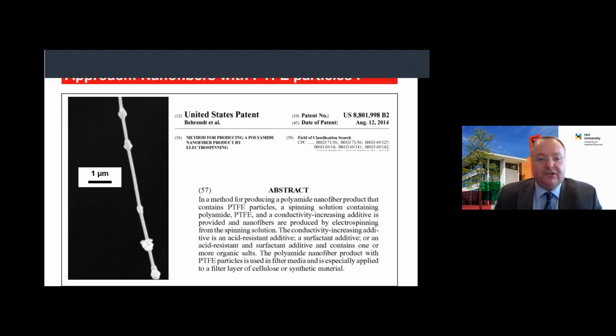Okay, here you see such a fiber. It's also an SEM picture. Here are PTFE particles. We have evidenced the presence of these PTFE particles with EDX. We could see that there is a lot of fluorine here in these nodes. And now the question is how we can realize this spinning process. I made a lot of experiments and found out. Please remember the spinning process.